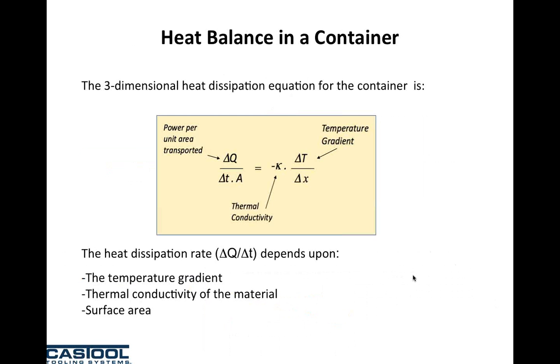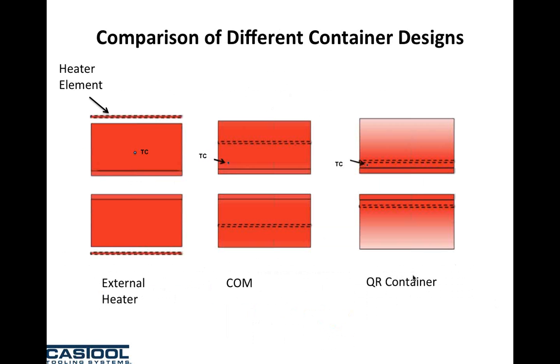So if you compare three different container designs, you can place your heater in different locations. Still, a lot of people use external heated elements. We see some people use center of mass heaters, and we think the proper one, or the best one, is if you put a heater close to the liner. You can see from this diagram clearly it depicts the temperature within the container.